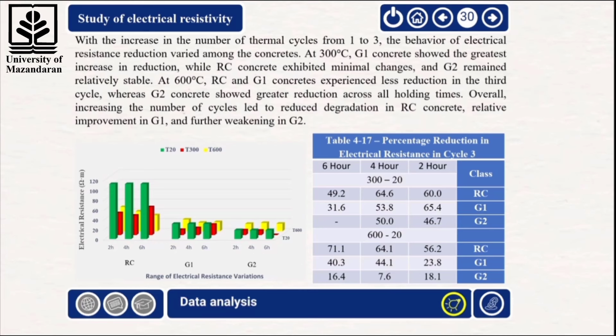Overall, increasing the number of cycles led to decreased resistivity loss in RC, relative improvement in G1, and further deterioration in G2. The table corresponding to 3 thermal cycles shows the percentage reduction in electrical resistivity over different holding times.